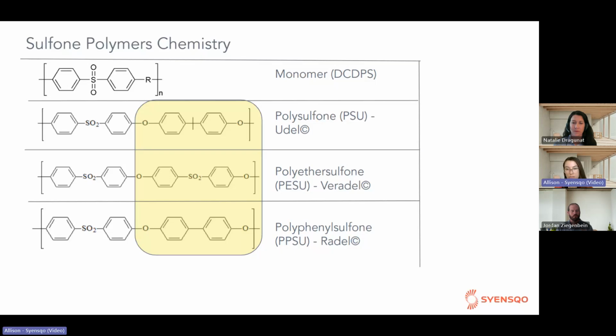This slide just shows the difference between the polymers in the sulfone family. Each material has a different R group, which influences the physical performance of the polymer. So as you move from Udel to Veradel and then Radel, you're actually increasing that aromatic content that I talked about earlier. You're increasing those rings in the backbone, which can contribute to that stability, and you'll get a little bit better thermal performance, a little bit higher Tg. And this really highlights why Radel PPSU is the highest performing in the sulfone material, and we'll see where it's used and how we capitalize on its capabilities in the healthcare space.